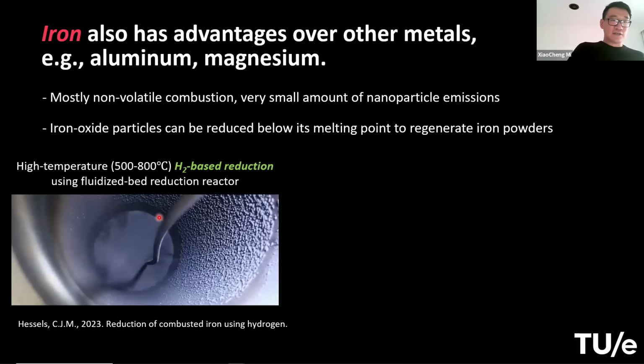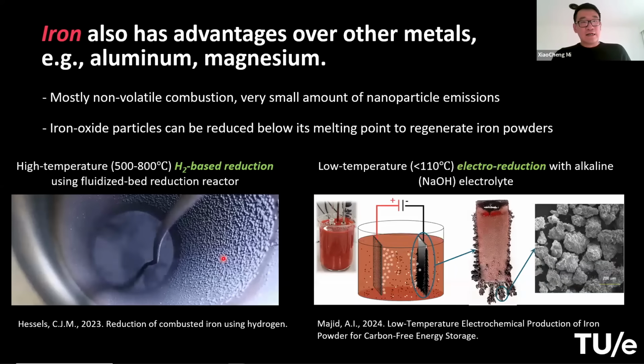What you are seeing here is a top view of a fluidized bed. So this bubbly feature is actually hydrogen gas passing through the bed. In this way, you can reduce iron oxide back to iron. And another way, we can do direct electrolysis. So we directly use electricity. You apply the voltage over this electrolyte, which is an alkaline solution. You dissolve your iron oxide in there, and the iron can be deposited on the cathode surface. In such a way, you can achieve a much lower temperature electrolysis, even below 110 degrees Celsius.